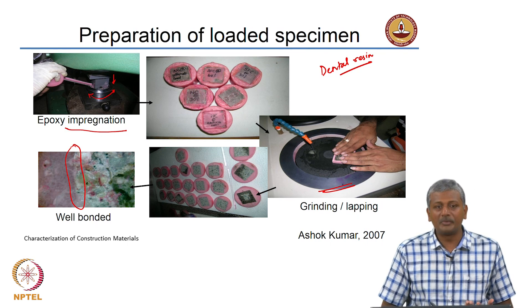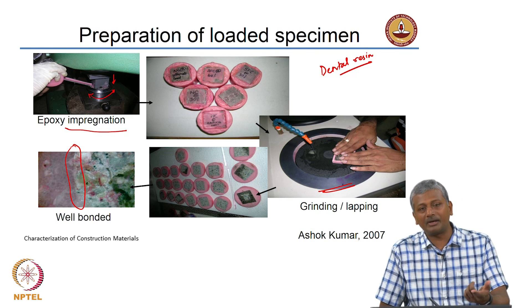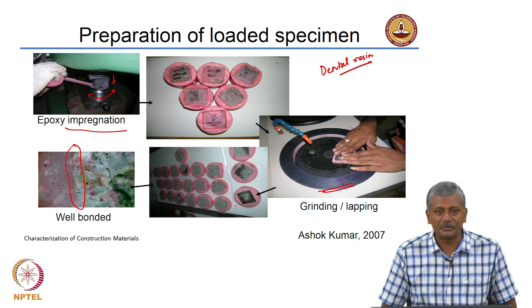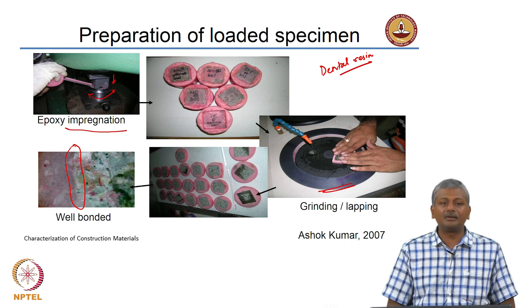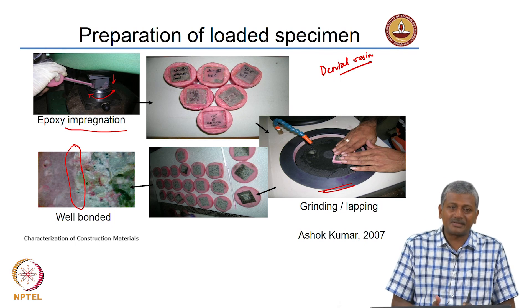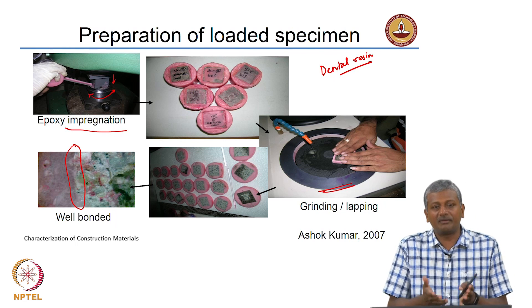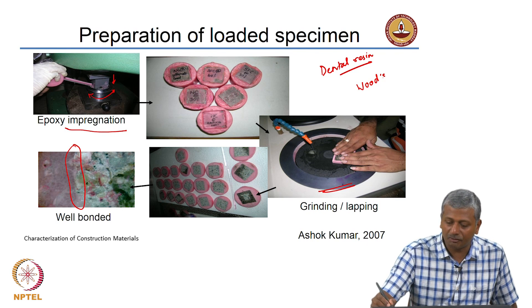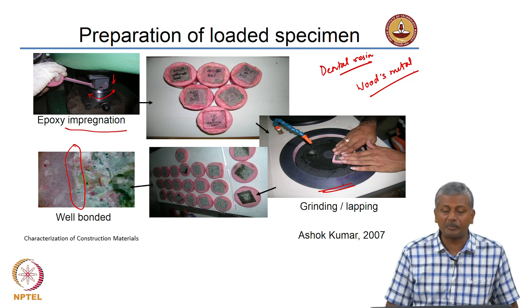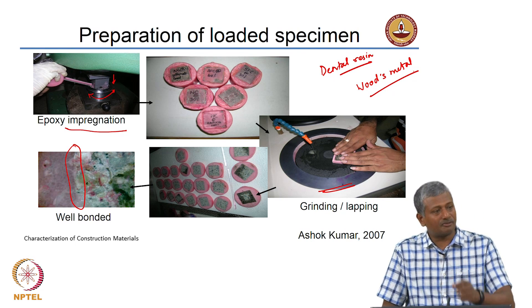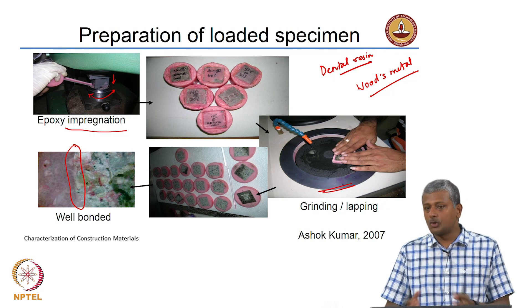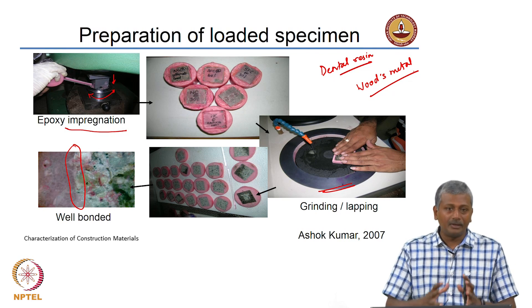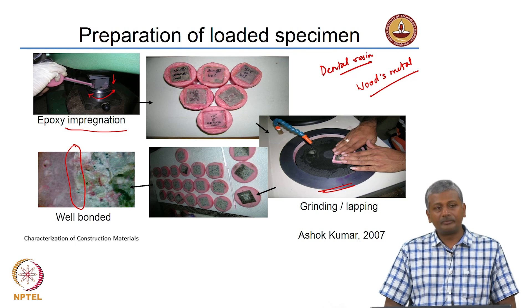Polymers tend to creep significantly, and the concrete would also be creeping during load maintenance, but we are only talking about 5 to 10 minutes, so incremental structural changes are limited — which is why we need the resin to set very quickly. There are other techniques; people have used something called woods metal, which has a much lower viscosity and is able to penetrate the material to a much better degree, holding the specimen intact and preventing it from failing.